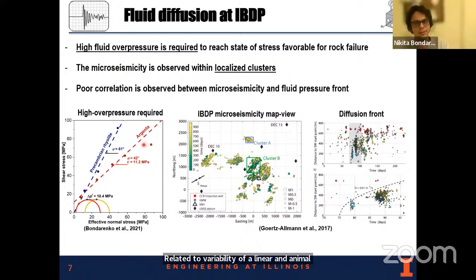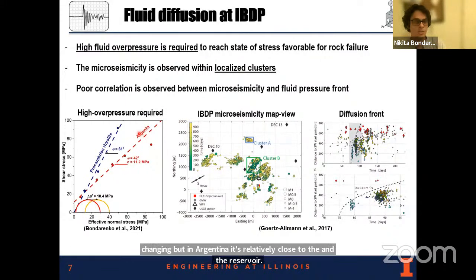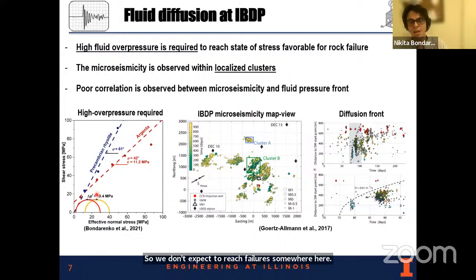I would say we are still working with very limited data. For the Precambrian rhyolite, we had only 3 data points at all, because when we tried to prepare the specimens, they were just failing along some pre-existing planes. For Argenta, we were more successful. So it might be some variability due to the heterogeneity of the specimens. But this high level of stress, in Argenta, is relatively close to the state of stress in the reservoir, so we don't expect to reach failure somewhere here. So most likely it's in this area.